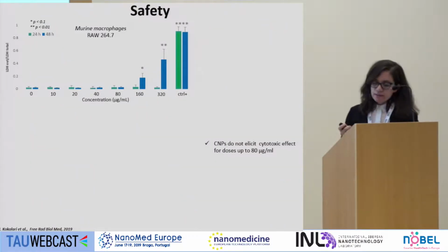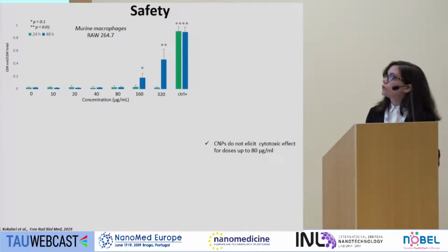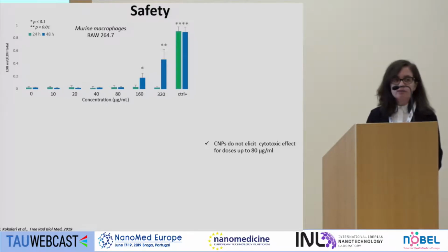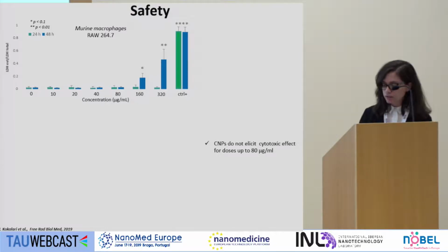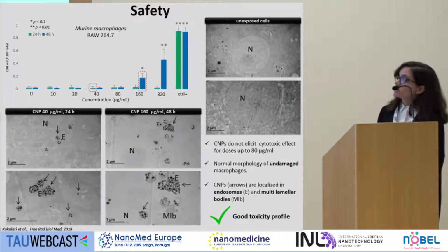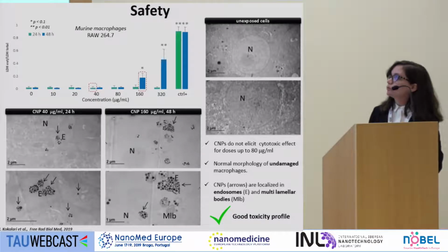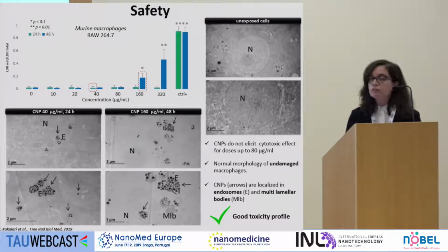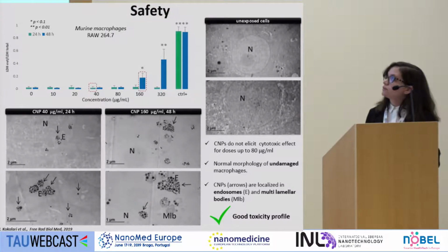The cytotoxicity was evaluated firstly in macrophages, and we found that nanoparticles do not exhibit toxicity for doses up to 80 microgram per milliliter. And also, we evaluated the interaction of the carbon nanoparticles with the macrophages by TEM, and we found that nanoparticles are efficiently internalized, and also we observed a normal morphology of undamaged macrophages.